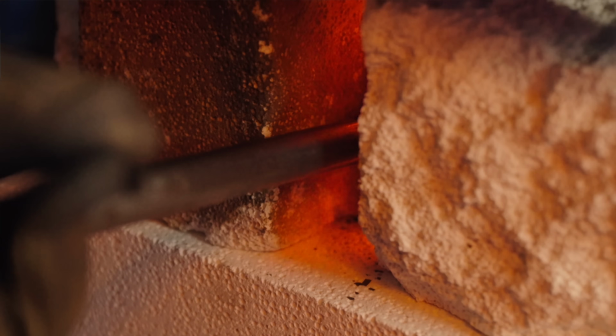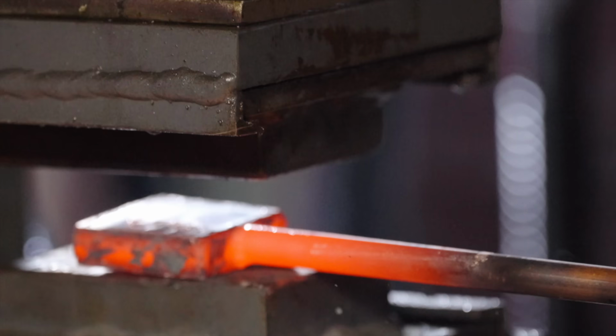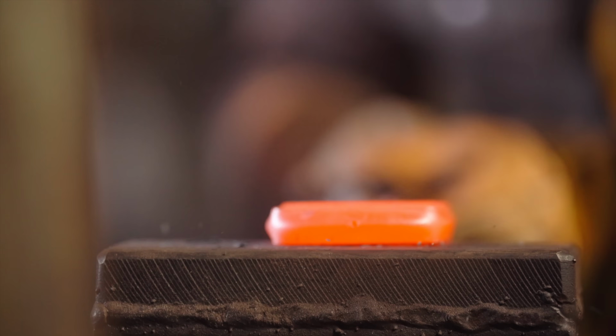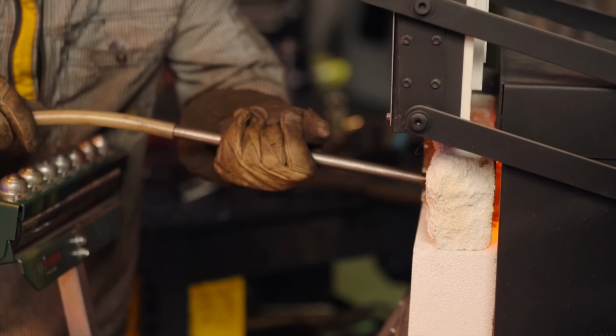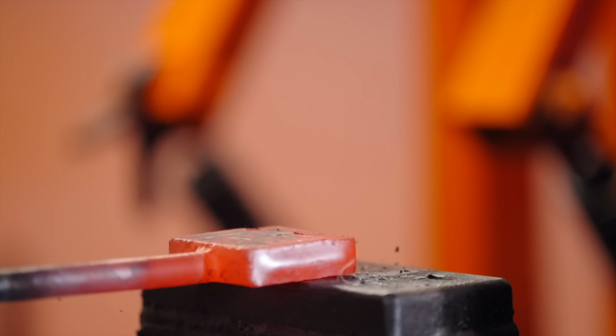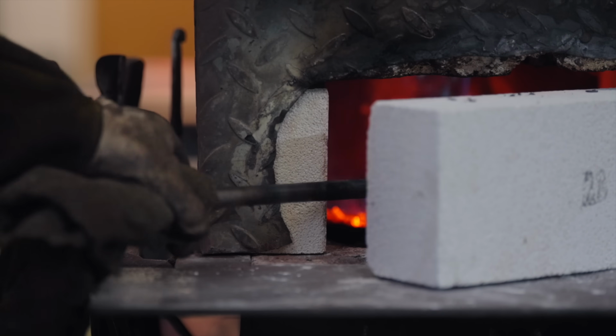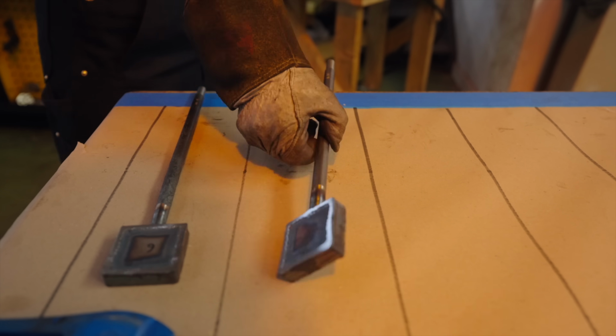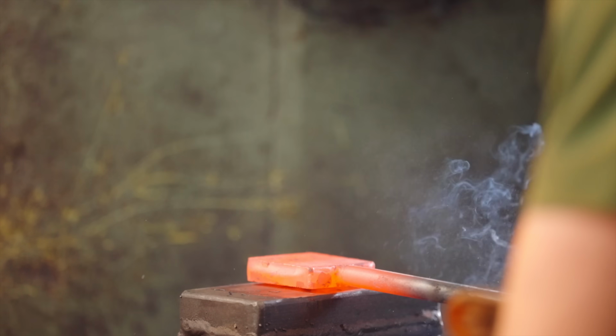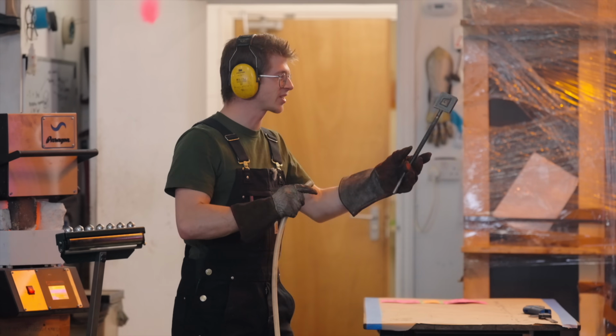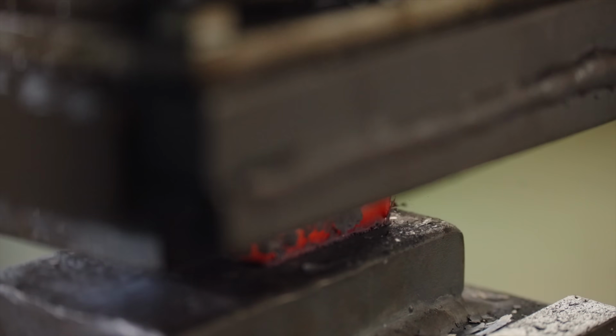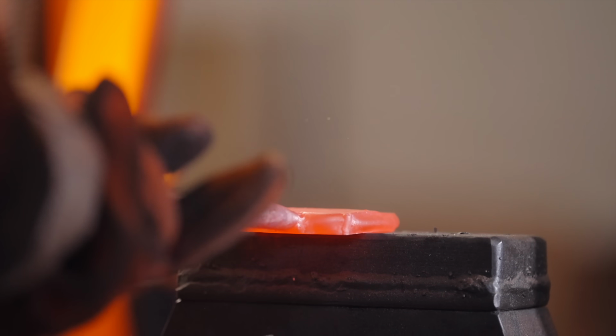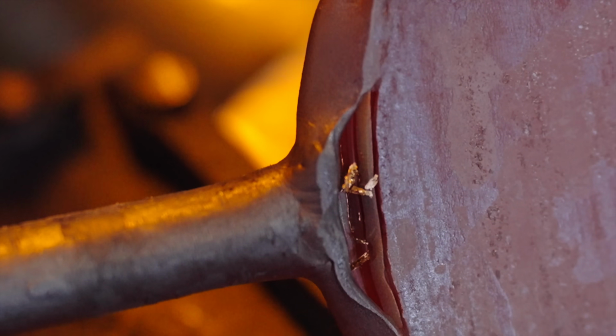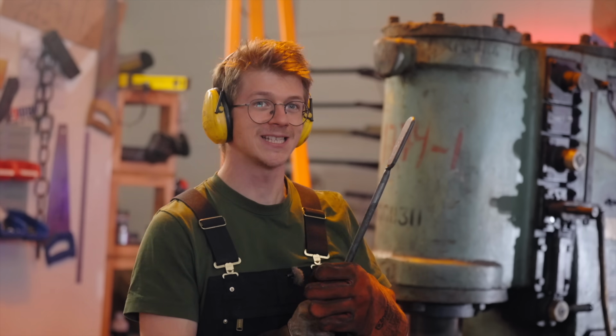This is number 2, 0.7mm copper interlayer. Billet 3. Billet 4. Billet 5. Billet 6, gold leaf. Look inside. You can see the gold foil. That's nuts. That is actually the first of any of the interlayers that I've seen during the forging process.